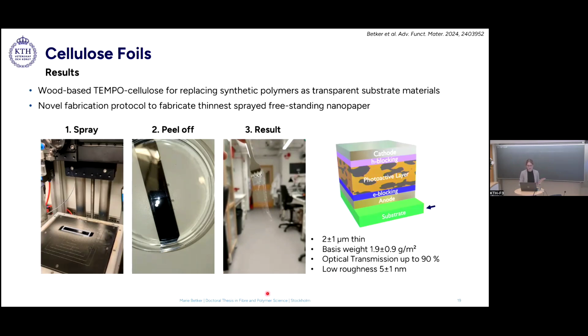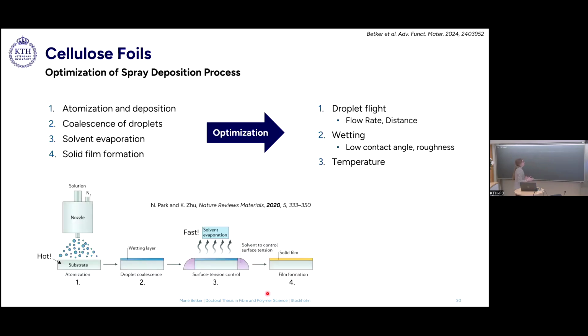Okay, so how did I do it? In general, the spray process can be divided into four different steps. The first step is you take your solution, fill your nozzle with it, and then you press the solution through the nozzle opening under a certain pressure. This leads to the atomization of the liquid into tiny droplets, which are then deposited on, in our case, a hot substrate. In the second step, the droplets coalesce and form a wetting layer. Third step, we have the evaporation of the solvent, and the fourth step describes the formation of the solid film.